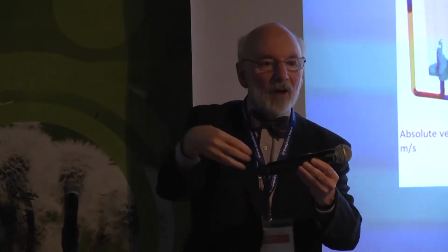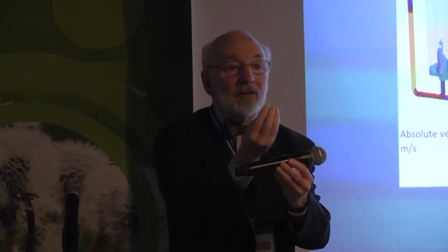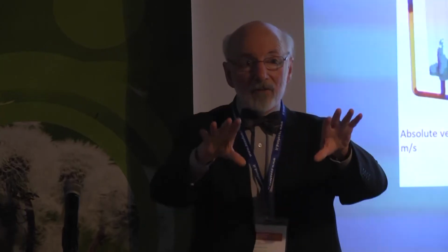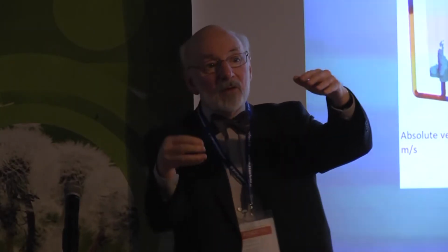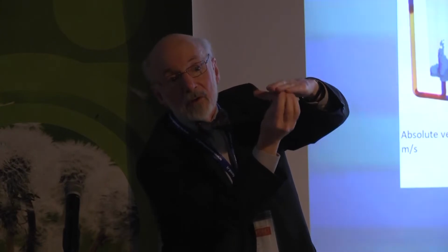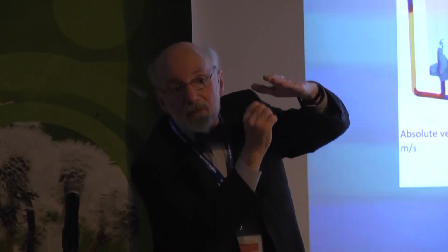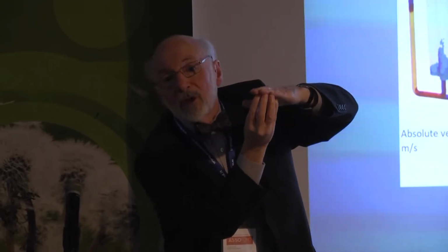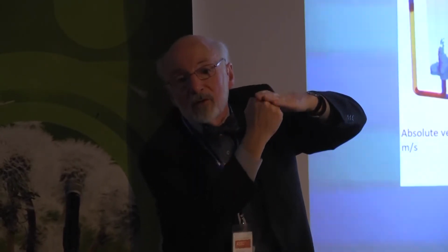Because bubbles arrived, they would go up the gate, they would sit under the filter, and what we know from our X-ray video studies is that, first of all, a small bubble arrives under the filter and just sits under the filter. It hasn't enough buoyancy to push through. But then another bubble arrives, and now it becomes twice as big and twice as much buoyancy force.